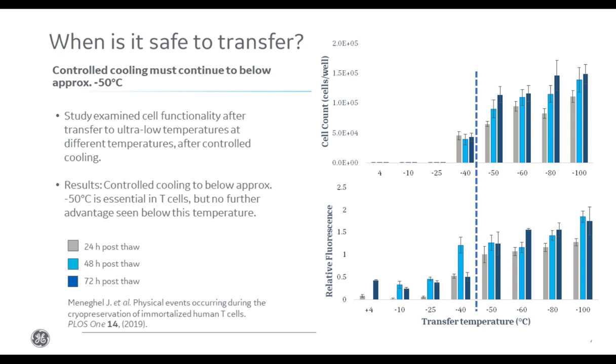As you can see on these graphs displaying viable cell counts above and cells' metabolic activity below over 72 hours of culture post-thaw, for the different endpoint temperatures tested, we found a sharp drop-off in viability for samples transferred at warmer temperatures than approximately minus 50 degrees, but no additional advantage of controlling the cooling below this point.